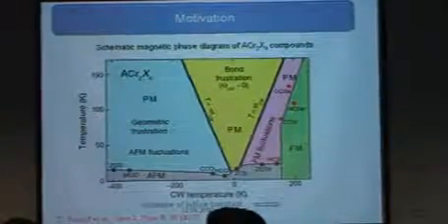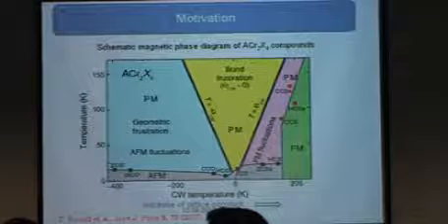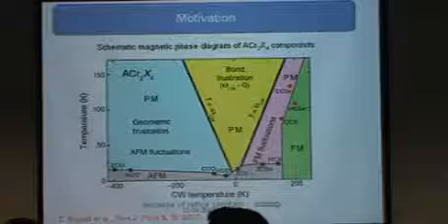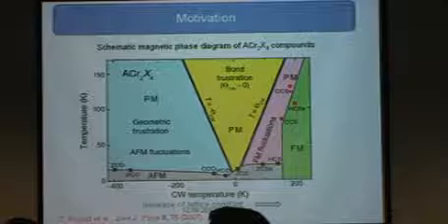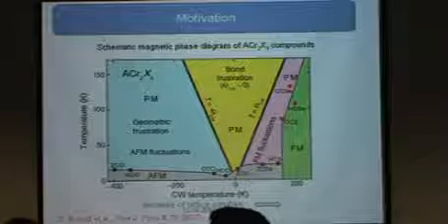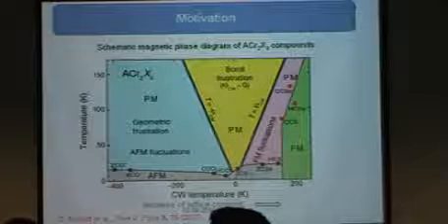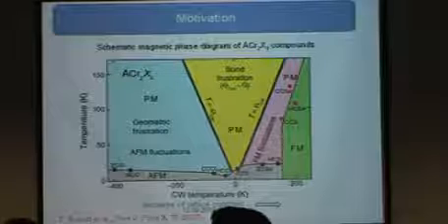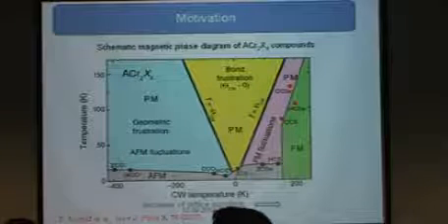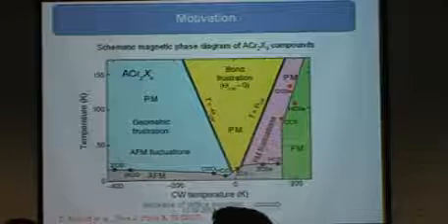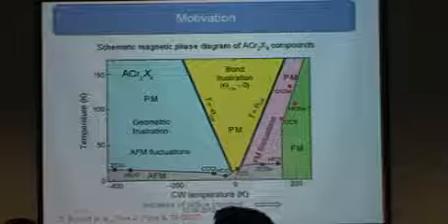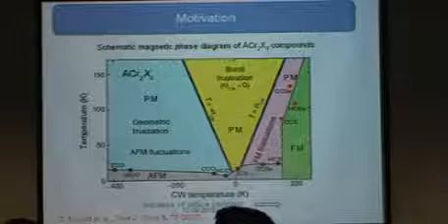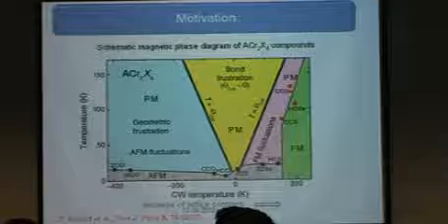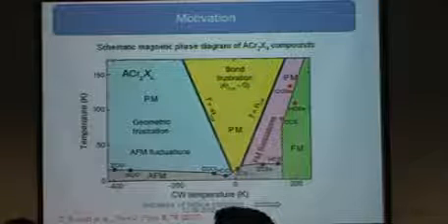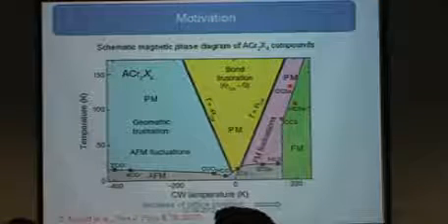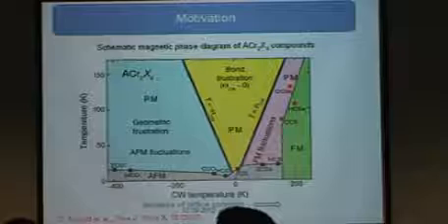You take -400 Kelvin. Can you really measure that -400 Kelvin? No, that's the point. As Dr. Servi also mentioned, when you measure this Curie-Weiss temperature, you get it through the magnetic susceptibility: you check the change in curves and then extrapolate to where it cuts. If it goes to the negative side, then you measure it as negative. That's what I understood.